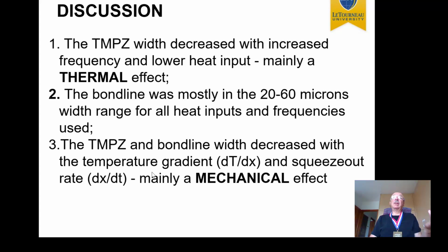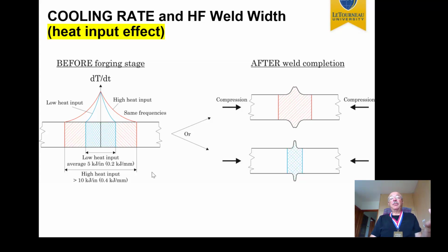So we started focusing on the fact that the bond line is a remnant of the mechanical cycle more than of the thermal cycle because it did not change much. So we came up with several theories. Here is one, the cooling rate effect.